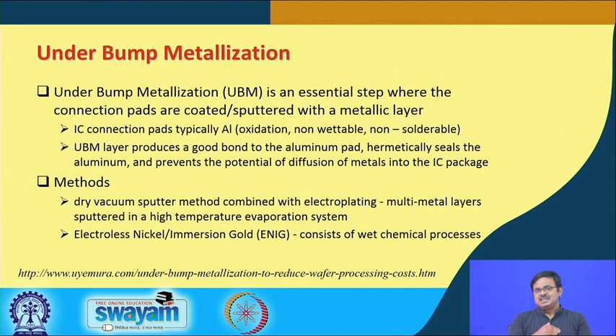Aluminum gets oxidized almost immediately. If you expose pure aluminum to air, an oxide layer forms on top in no time. And this oxide layer is typically electrically non-conducting. So, it is not a desirable coating on the surface of aluminum, especially for the application that we are talking about. Second one is aluminum is non-wettable, it is non-solderable, you cannot solder aluminum.